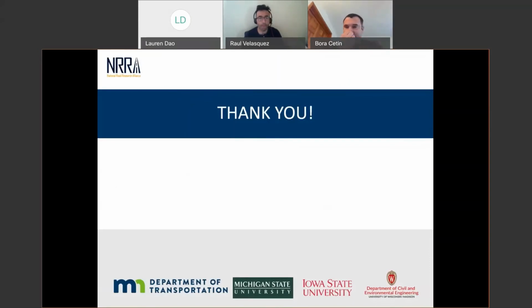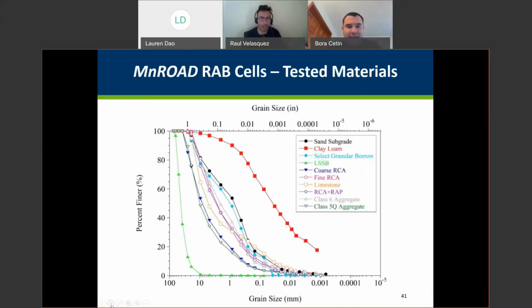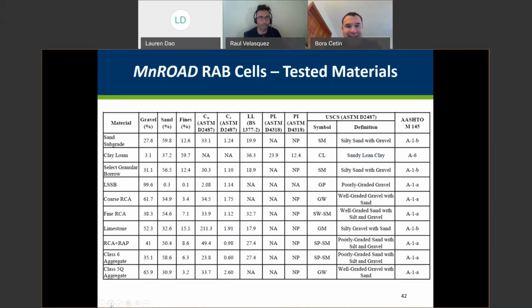Okay. So the first question was, early on in the presentation, please describe the composition of RCA, and I'm not sure if you ended up going through that or not. Yes, so Raul, maybe we can show that table that we had at the additional material slides. If you mean how much RCA we had in these materials, it was very challenging. We couldn't really get that, but coarse RCA, fine RCA, and class 5Q were predominantly RCA materials, like 80–70% that we could guess. And the RCA-RAP and class 6 aggregates were predominantly RAP materials. I hope that answered the question. And this table shows the typical, more detailed definition and characteristics of the RCA materials.